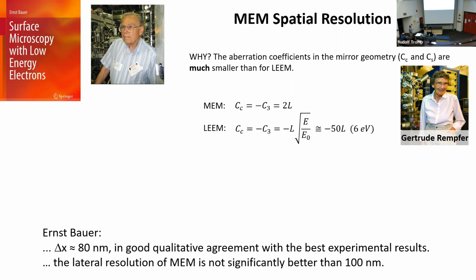Yeah. If I look at the aberration coefficients, and these were worked out by Gertrude Rempfer a long time ago, in mirror mode, they're given, so this is the chromatic and the spherical aberration coefficient, 2 times L, where L is the distance between the sample and the objective lens, 1.5 millimeters. So the aberration coefficients are 3 millimeters. In LEEM, they're more like 10 centimeters.